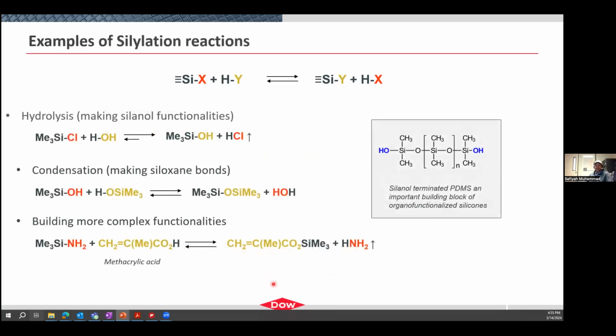So again, at the beginning, we talked about taking quartz, turning it into silicon metal, then we hydrolyze it and condense it. Hydrolyzation of your chlorosilanes is a silylation reaction. Your heteroatom is chloride in this case, and the active hydrogen species is actually water. So we're turning all of the silicon chloride bonds into silicon hydroxide species, or silanol species. And we create HCl, which is a gas, and it is driven off through vaporization, right? So that reaction goes very quickly. It's a spontaneous reaction. It actually heats up, so you control your exotherm with ice baths or temperature control, right? That reaction happens very rapidly.